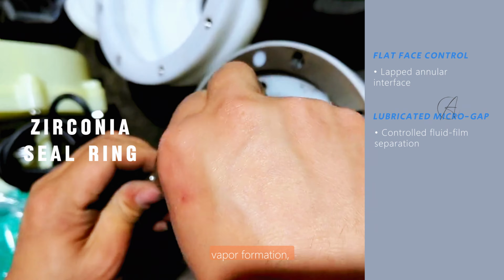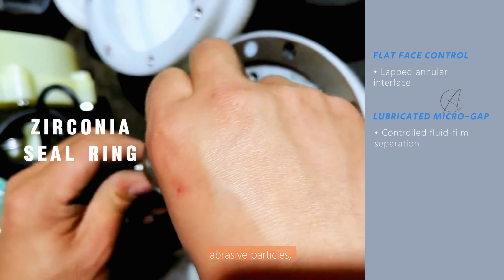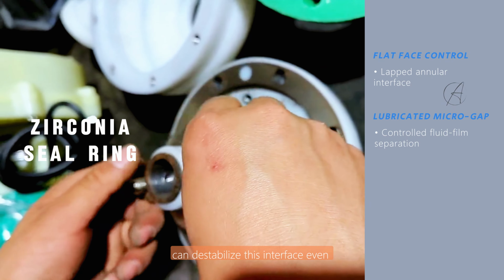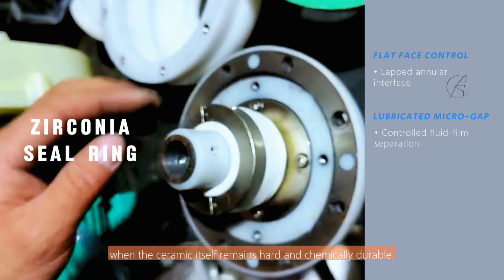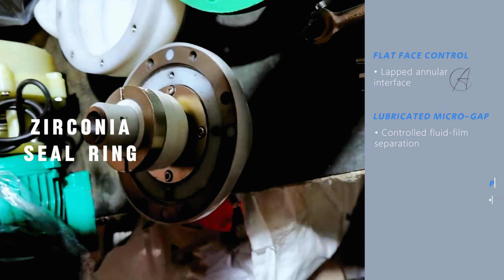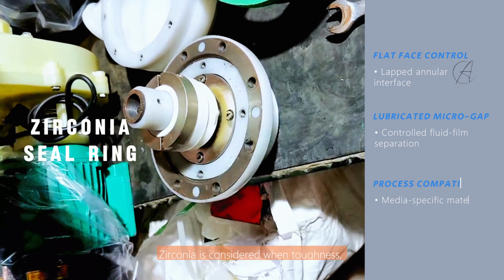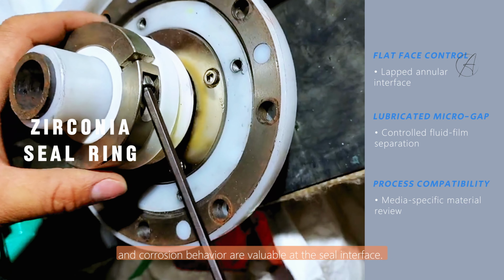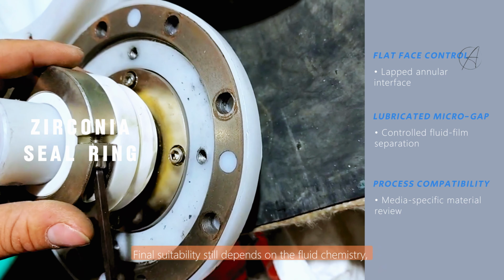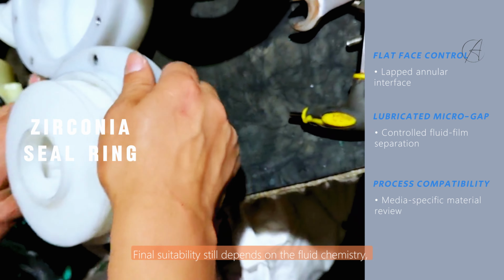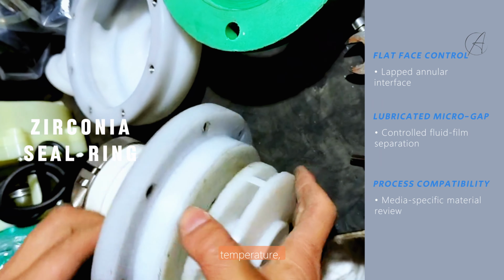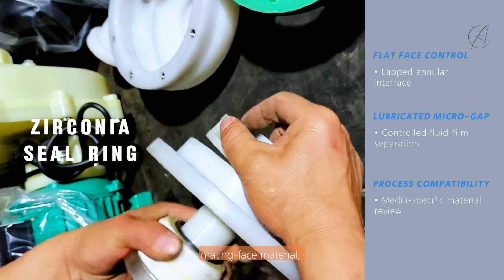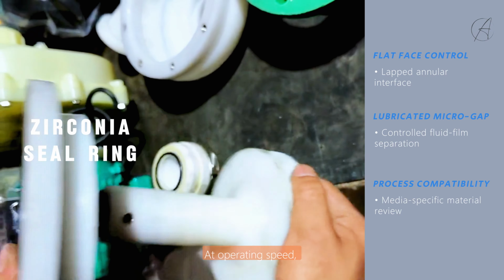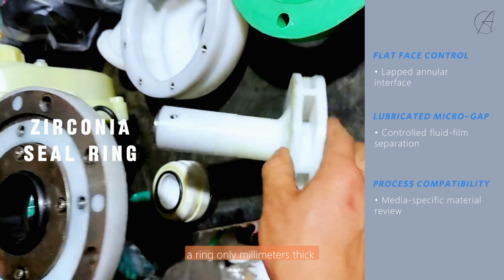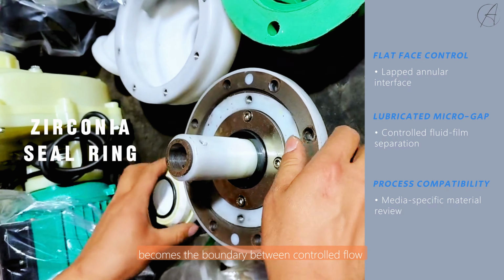Dry running, vapor formation, abrasive particles, or interrupted cooling can destabilize this interface even when the ceramic itself remains hard and chemically durable. Zirconia is considered when toughness, wear resistance, and corrosion behavior are valuable at the seal interface. Final suitability still depends on the fluid chemistry, solids, temperature, pressure, speed, mating face material, and lubrication regime. At operating speed, a ring only millimeters thick becomes the boundary between controlled flow and an unintended leak path.